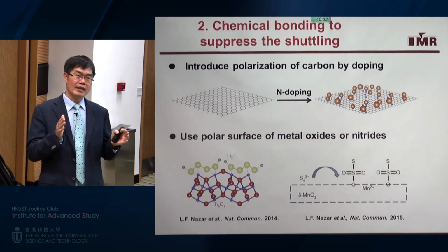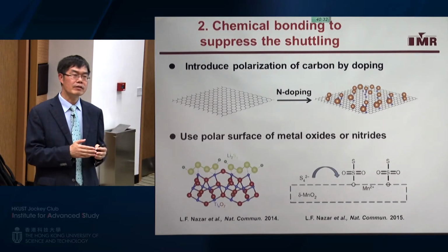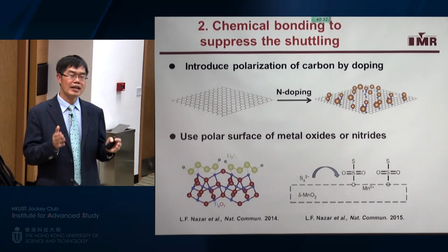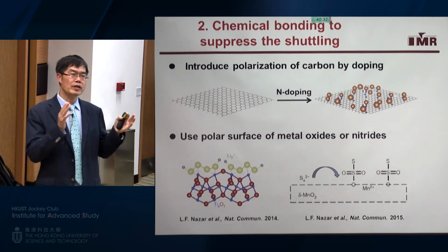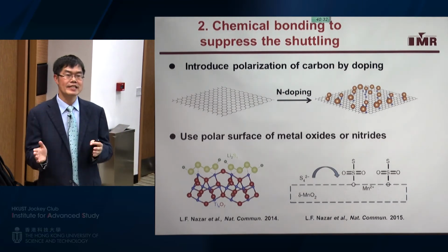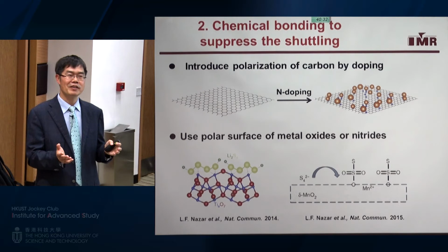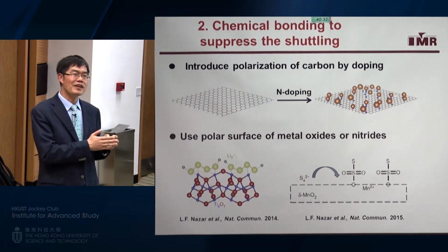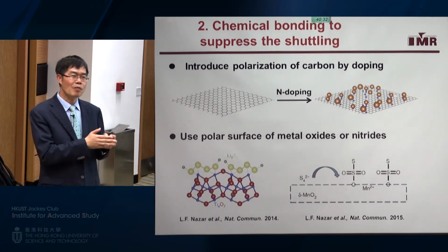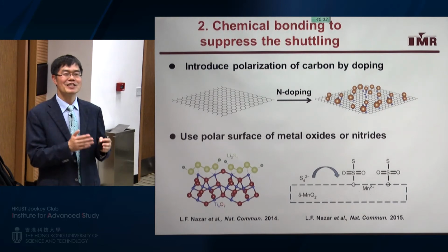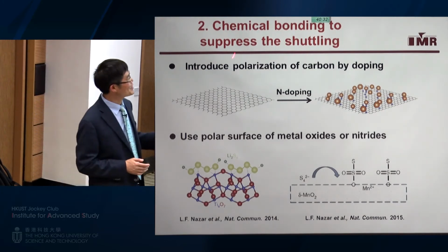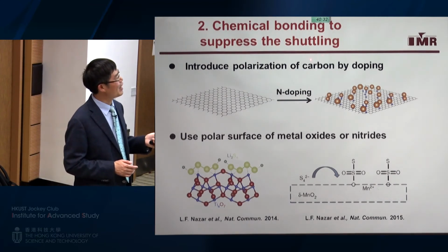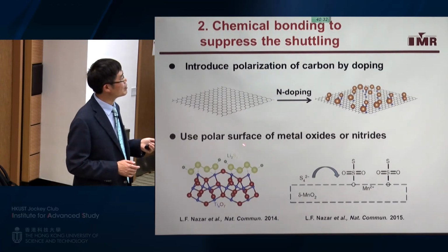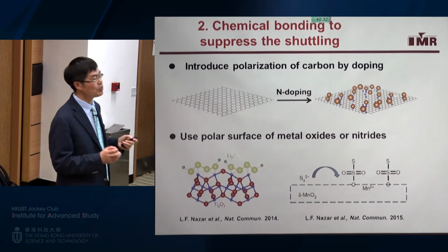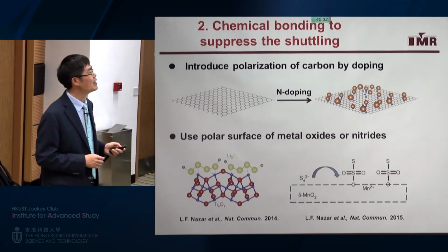So actually, polysulfide is a polar molecule, and the electrode also is a polar molecule. That means the interaction between polysulfide and electrode is a polar interaction. But carbon is a non-polar molecule, like graphene. So that means graphene and polysulfide have a non-polar and polar interaction, which is weaker than a polar interaction. Therefore, we think we need to introduce polarization on carbon by doping, or to use polar surfaces of metal oxide or nitride to improve the chemical interaction.